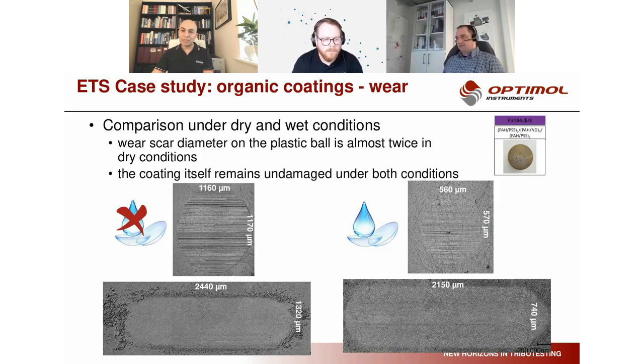And you can see here, I just put some microscopic images after the test. One, the so-called, let's call it purple coating, had a relatively high wear under dry conditions and a very low wear under wet conditions. But interestingly, if you look at the wear tracks, even if there is a relatively higher amount of wear under dry condition, the wear track is very smooth. And this is what is relevant in the contact between the eye and the lens, that the surfaces always remain very smooth. Otherwise, you will have irritations.